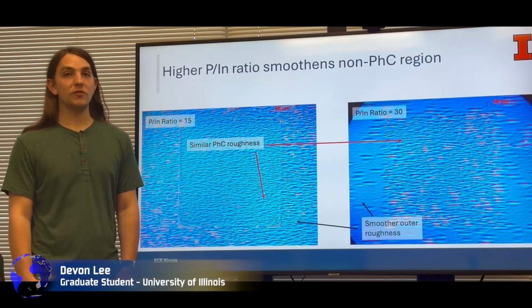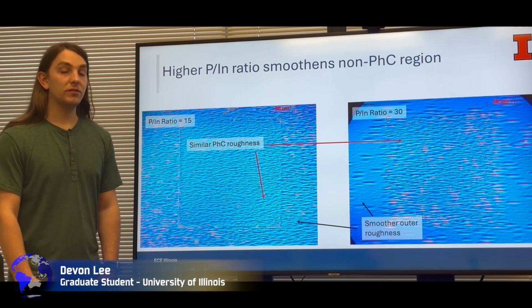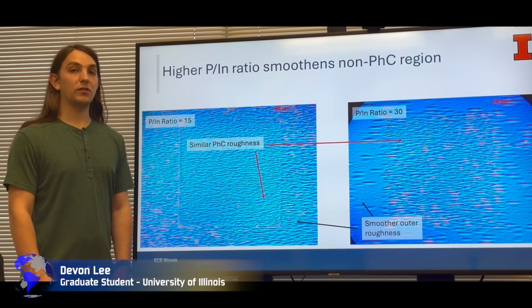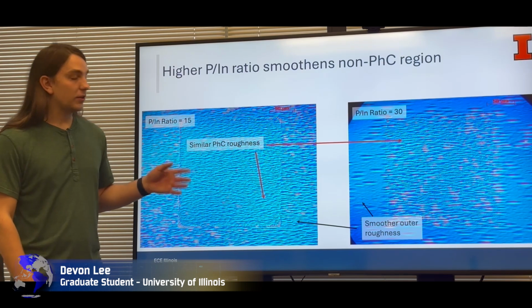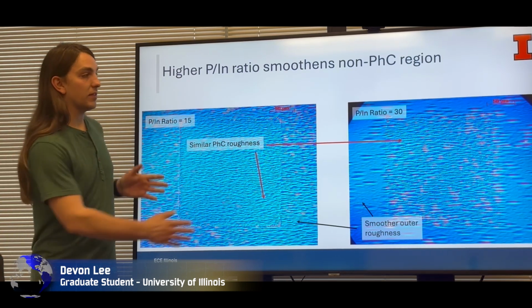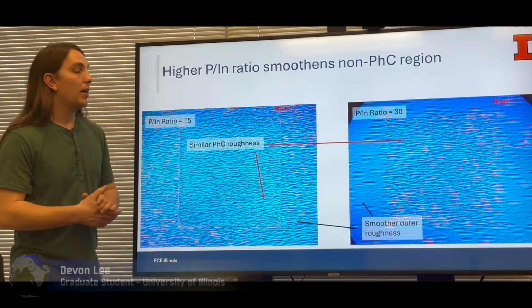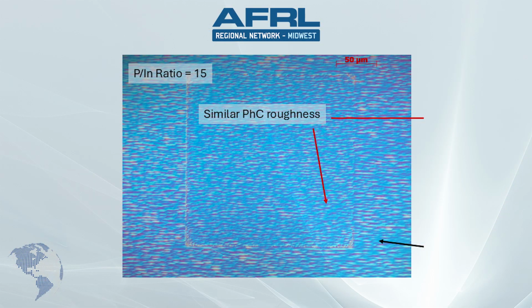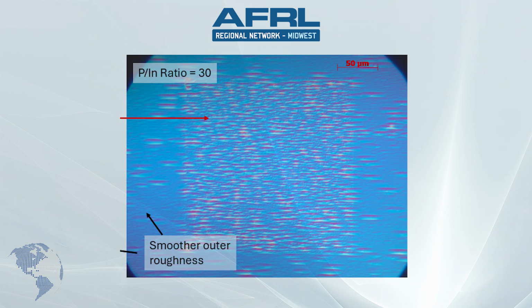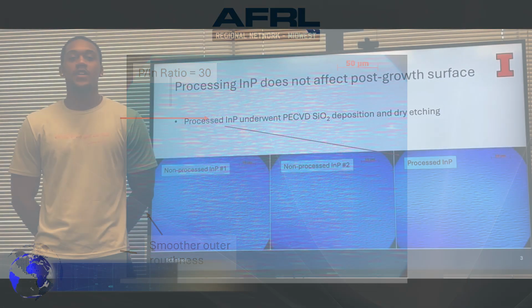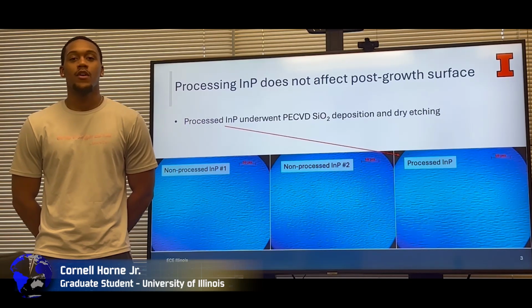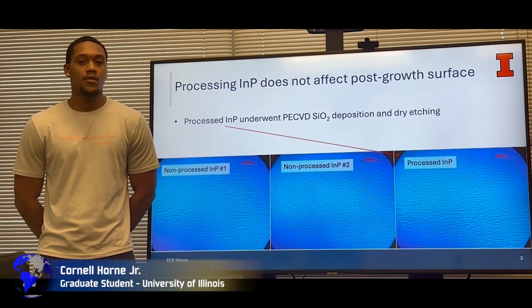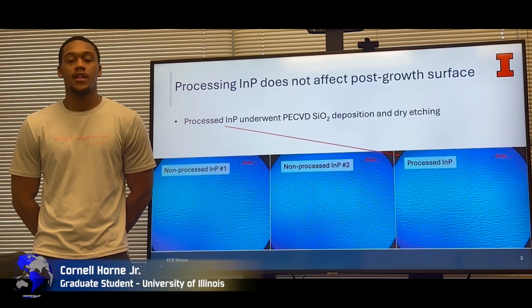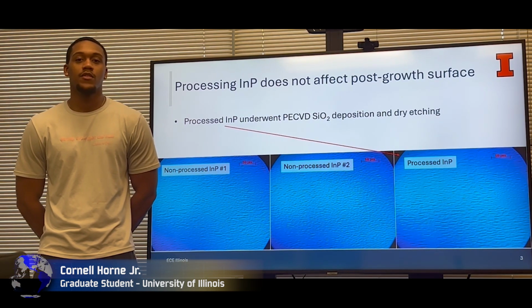One of the growth-related achievements that we accomplished in the last segment was decreasing the roughness of the surface of our devices. While the photonic crystal itself is still contributing to roughness, you can see the inner parts of the squares in these images. Increasing the phosphorus to indium ratio significantly decreases the roughness outside of the photonic crystal, which allows us to maintain our selective growth regime while not suffering a roughness penalty, at least outside of the photonic crystal region. We wanted to analyze if dry etching affected the surface roughness of the samples. So with one sample, we dry etched it, and another sample we did not, and there is no significant difference of the two in the surface roughness.